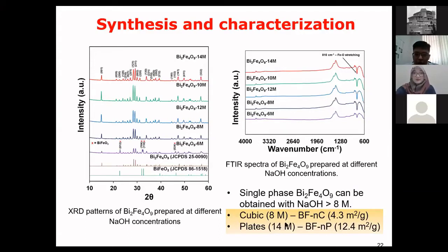As I mentioned just now, if you use 8 M, you will get cubic morphology. If you use 14 M, you will get plate-like morphology. So look at the surface area. It looks very low, right? 12.4 and 4.3 is still very low for catalysis. But of course, you have to remember that bismuth itself is very heavy, in the sense that it has high density. So for typical bismuth-based material, 12.4 is also considered quite large.